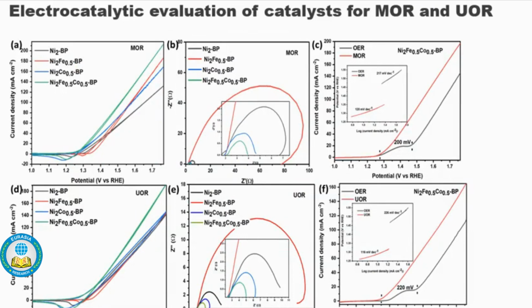To evaluate the activity of the prepared catalyst for methanol and urea oxidation reaction, CV measurements were performed in potassium hydroxide with either methanol or urea at a scan rate of 50, and linear sweep voltammetry at a scan rate of 10. The prepared electrocatalyst presented the highest MOR activity compared to the reference catalyst in terms of specific activity, and this can be attributed to the provision of more accessible active sites and the synergetic effect of the multi-elemental material that improves MOR.